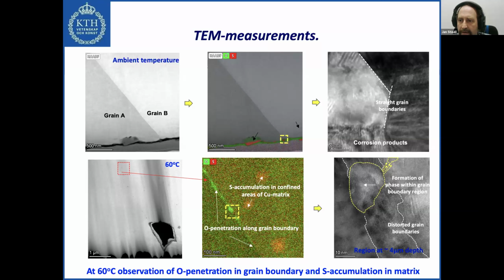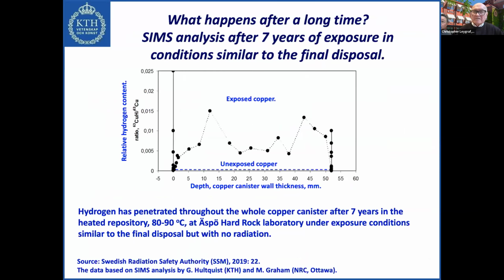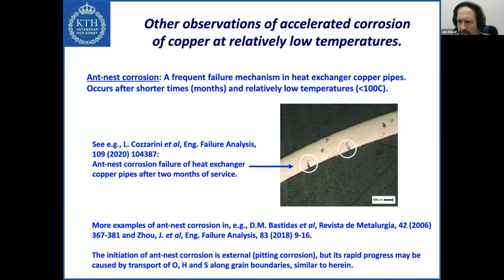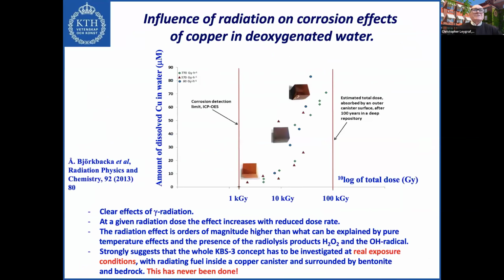Okay, other question from anonymous attendee. If the radiation effects are higher at lower dose rates, then the worst case must be when there is no radiation. The worst case, we can go back to this one, yes. Yes. Okay, so all of these results were at 3 different dose rates, 80 up to 770 grays per hour. And so the result at a certain dose, let's say this one here.